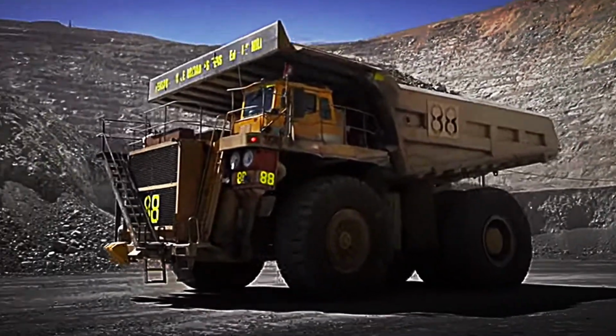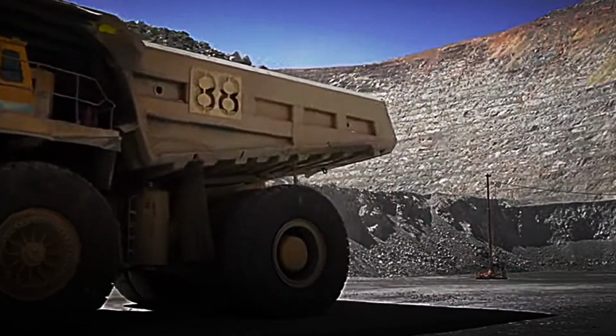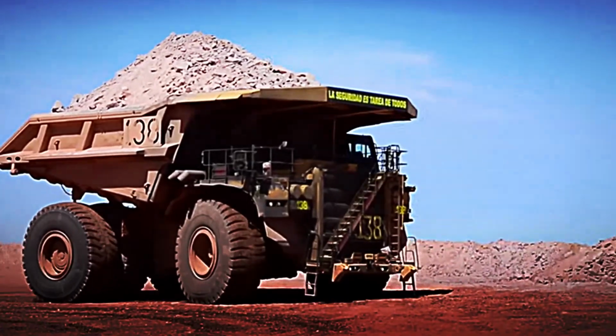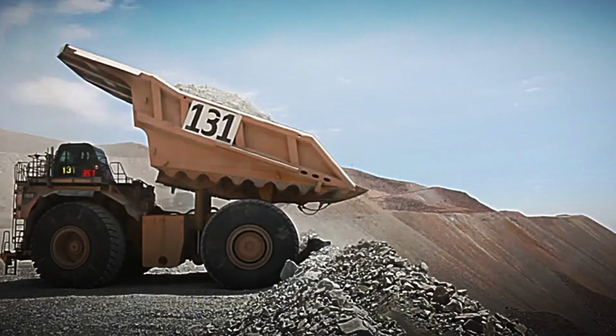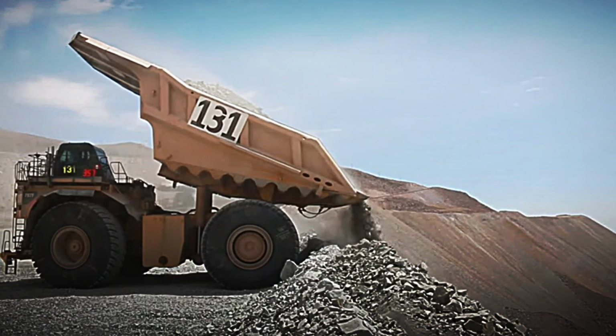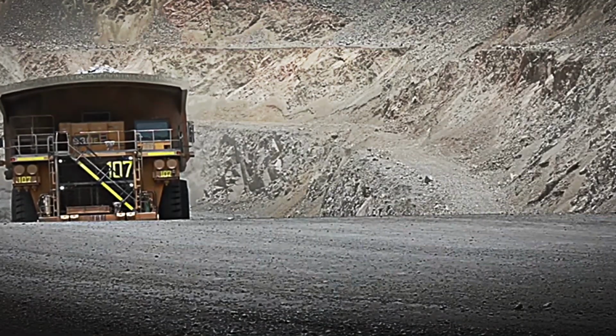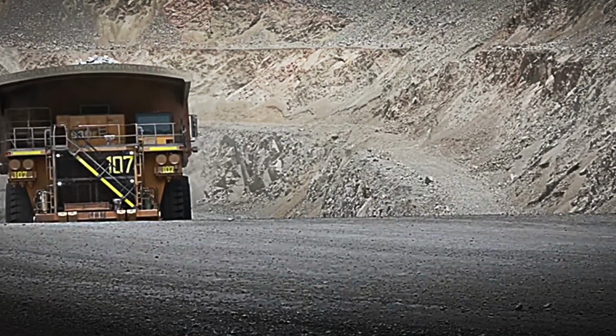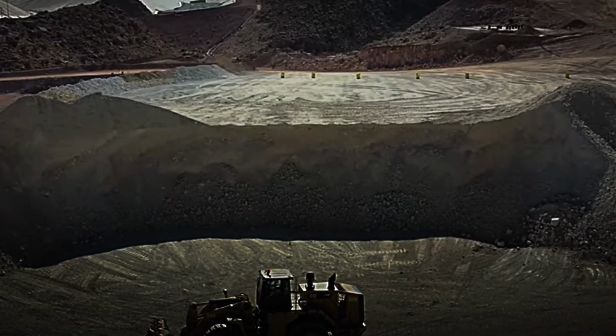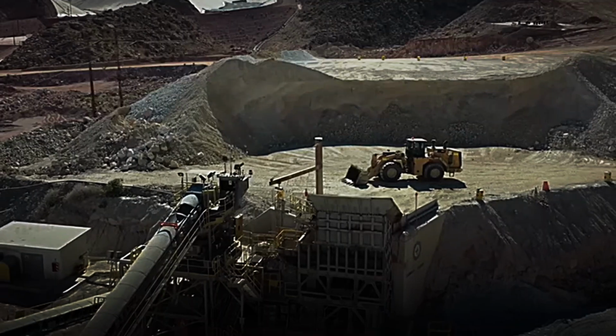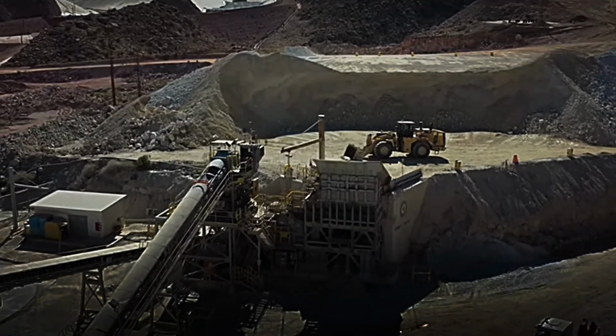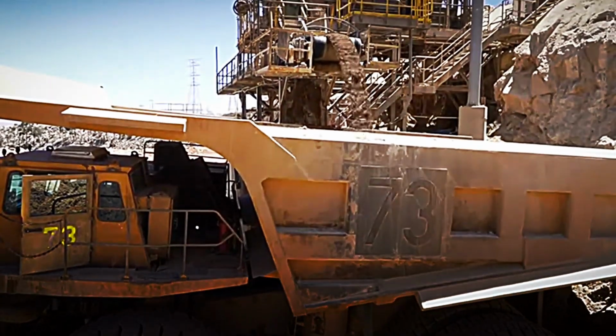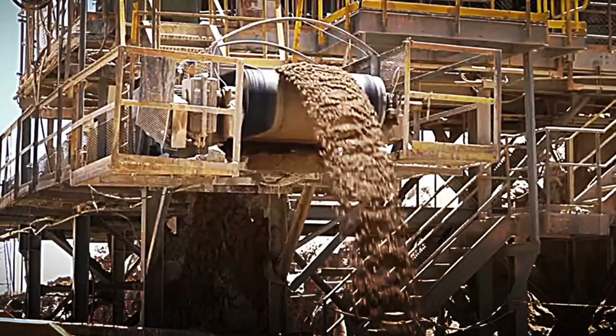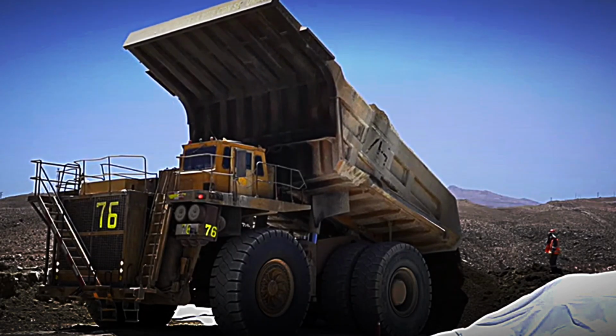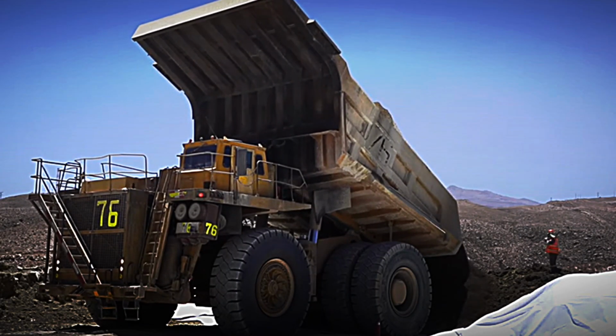Surprisingly, despite moving such volumes, the copper content in this material is very low. On average, less than 0.5% of the rock contains usable copper. This means that for every 200 tons of material extracted, barely 1 ton of refined copper will be obtained. This disproportionate nature demonstrates the magnitude of the logistical and energy effort required by the mining industry to meet global demand. To efficiently coordinate the constant movement of shovels, trucks, and excavators, the mine has a centralized control center.